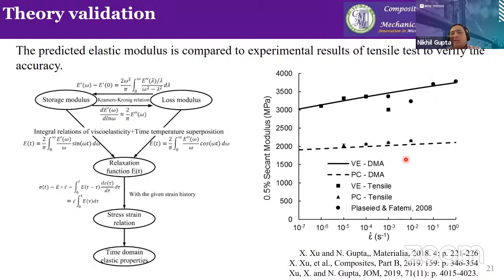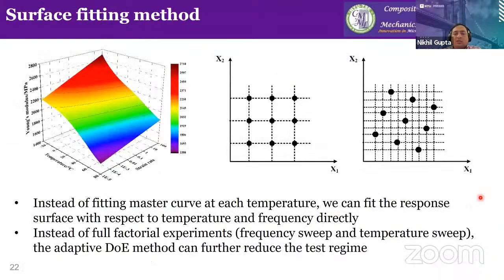So the data again is validated with a number of different polymers. Here you can see vinyl ester and polycarbonate data coming from DMAs in these lines, and we obtain data from some of our tensile tests and also tensile tests which are reported in the literature from other groups. And these could be at any strain rates, as you can see, within the same 10 to the power minus 6 to about 1 per second strain rate. And this matches pretty well. So the effort is reduced quite a bit, and that's important for viscoelastic materials.